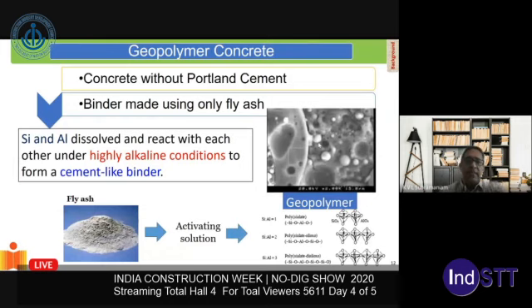Basically, for geopolymer production from a given fly ash, it is the reactive silica and the reactive alumina that are important. You take the fly ash, it is activated in an alkaline solution which contains dissolved silica. And when you subject it to elevated temperature curing, what you end up with is a geopolymer, which is a densely cross-linked network of silica and alumina, as I've shown here.